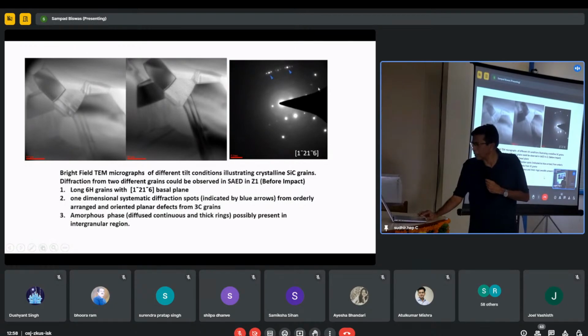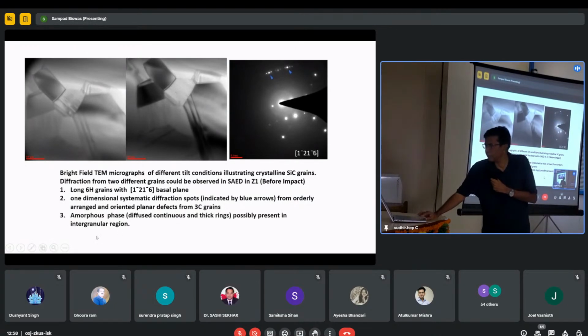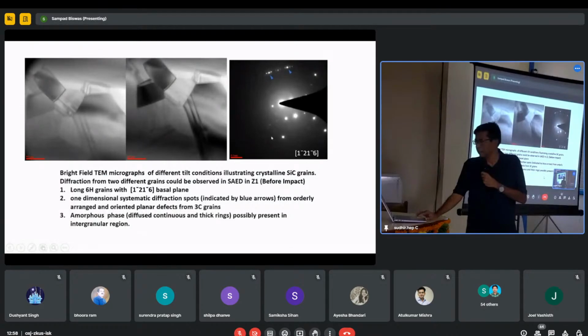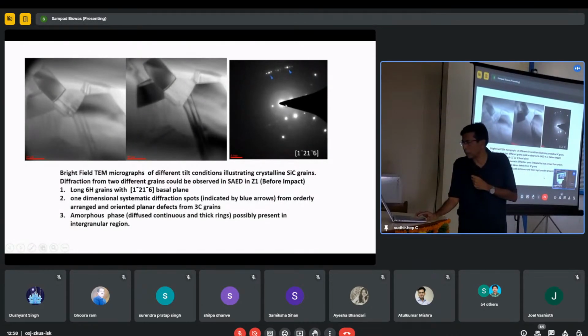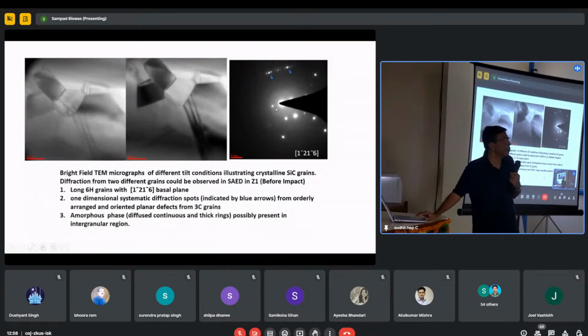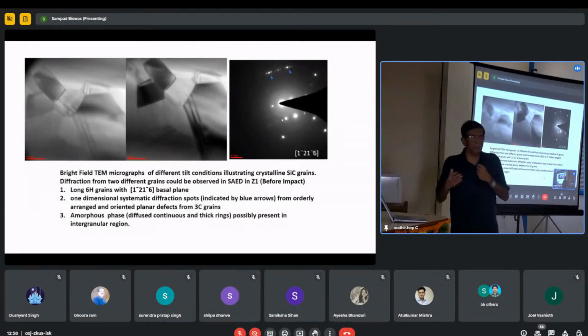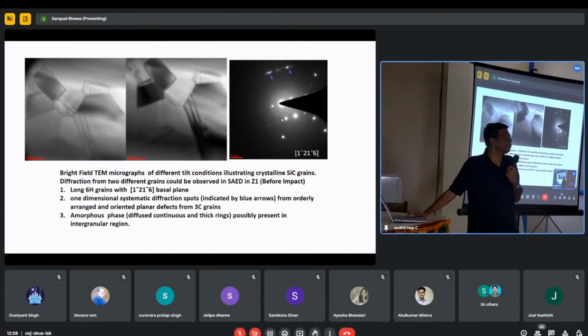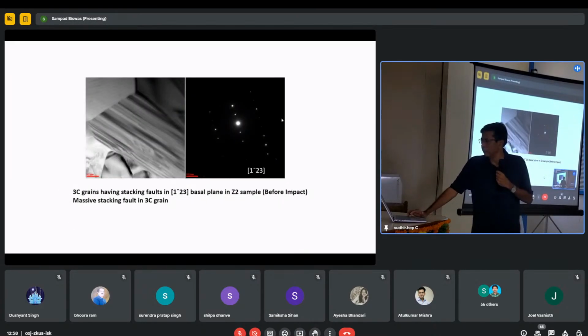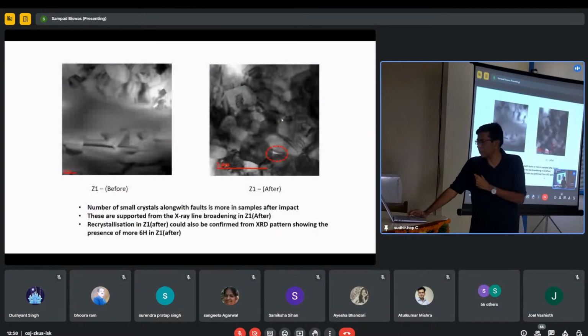Now, another important area we have found is the amorphous phase, with diffused rings we can find from this TEM. This amorphous phase is a very important area, and probably we presume that this was present during the sintering process, because other materials didn't have this amorphous phase. This is a 3C variety. I'm not going into details of it.